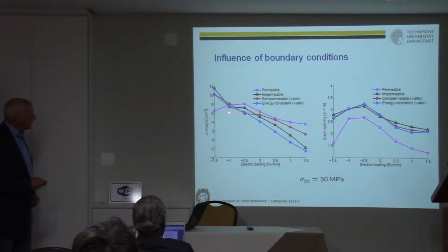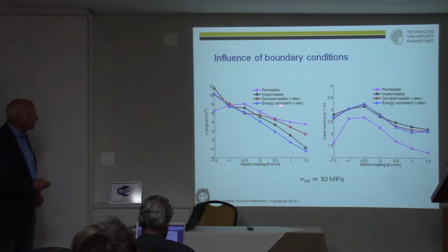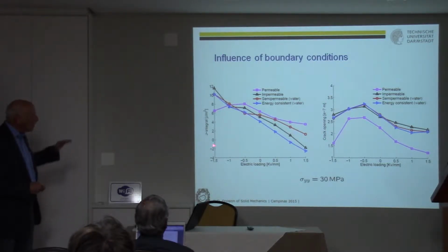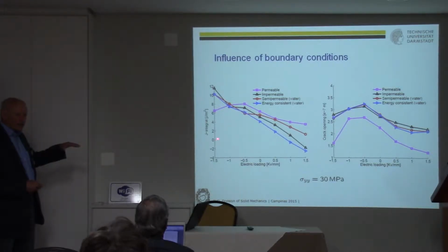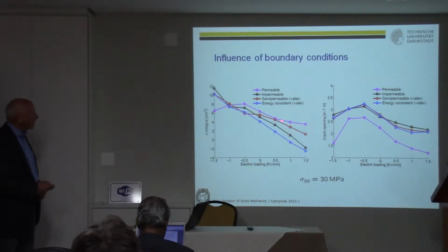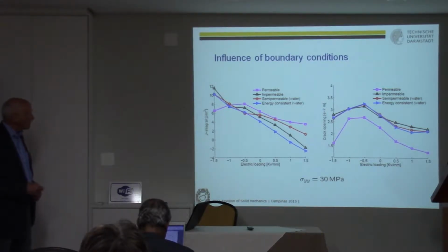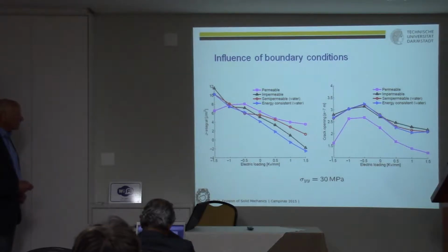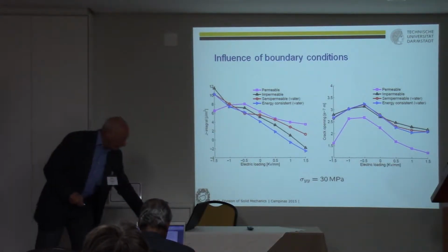And what perhaps one can see is that in the positive electric loading regime, these energy consistent boundary conditions lead to the lowest driving force, and the permeable boundary condition to the highest driving force. Okay.